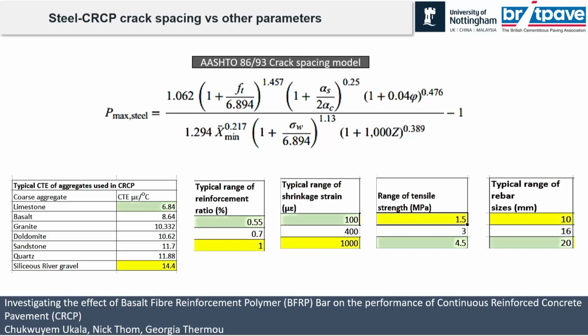We know that when we are working with CRCP, we expect to use aggregates ranging from limestone to siliceous river gravel, and they have a coefficient of thermal expansion as stated there. And we know that the coefficient of thermal expansion of concrete is highly influenced by that of the aggregate. So we use that value there, and we did the same thing for the reinforcement. Most likely, the reinforcement ratio of a CRCP ranges between 0.5 and 1.2, depending, but generally around 0.7, 0.65. So we took a range from minimum typical usage to a maximum that we believed was obtainable from the information we got.